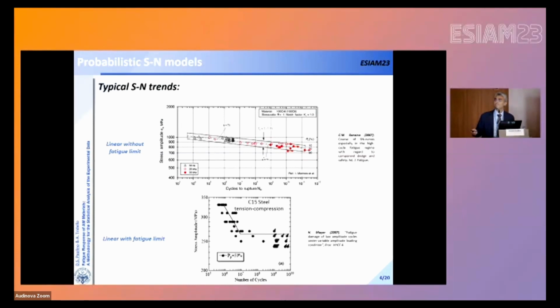The very simplest probabilistic SN model is related to the Basquin law. Linear trends applied all over the fatigue regime from high cycle to very high cycle. Another well-known trend is the linear fatigue trend with a horizontal plateau that is related to the fatigue limit region. So we have finite fatigue life and infinite fatigue life in such kind of SN trends.